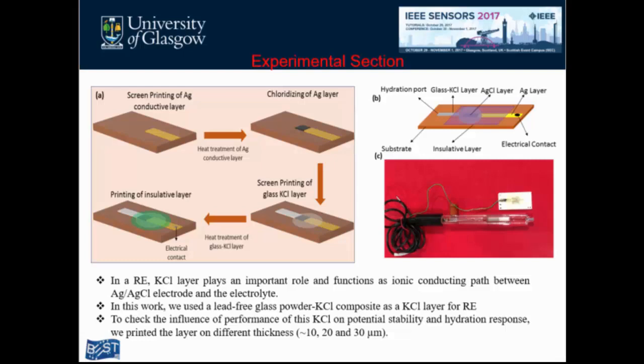Here you can see a comparison of a glass reference electrode and a thick film reference electrode. This is the commercial glass reference electrode, and this is the fabricated reference electrode. And here is the cross section. You can see here a hydration port, a substrate, an insulative layer, and an AgCl layer.